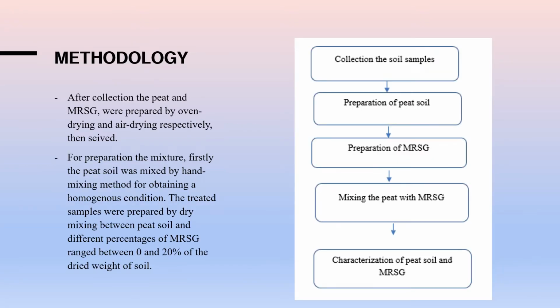Methodology of this paper. We started with collecting the peat soil and MRSG samples. After collection, we prepared the peat soil and MRSG separately by drying, then sieving. And before preparing the mixture, we mixed the peat soil alone by the hand mixing method to obtain a homogeneous condition. Then we started to prepare the treated sample by dry mixing peat and MRSG in different percentages, ranging from 0 to 20% of the dried weight of soil.